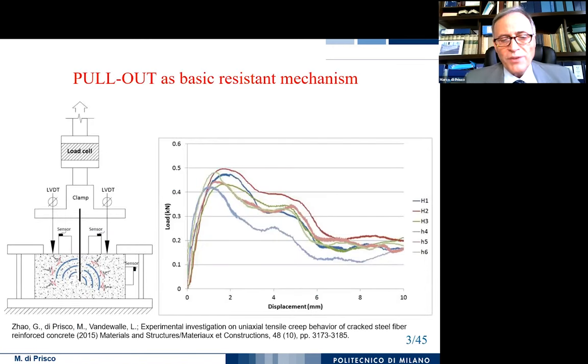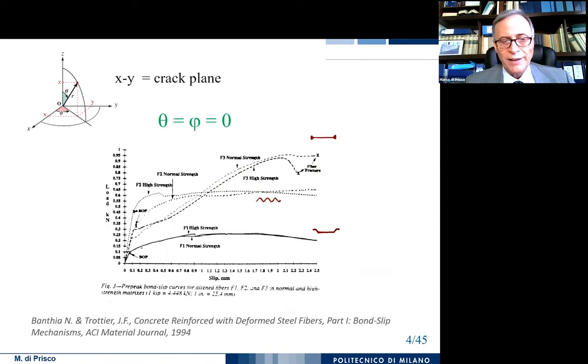I would start from this idea. If we extract just a single fiber from a block of concrete and we have different specimens, we always have a very important scattering because of the pullout mechanism. So the extraction of the fiber from the concrete specimen is due to bond. And that's the reason why, even if the fiber is only in a precise position, due to the difference in the embedment, we have a scattering. So this is a very important feature of our material.